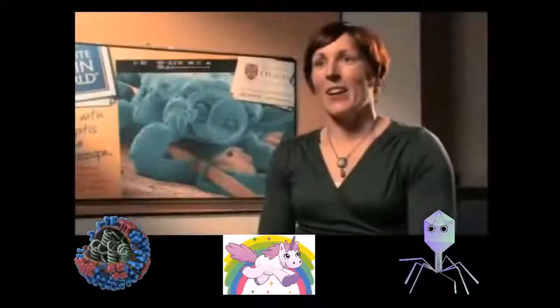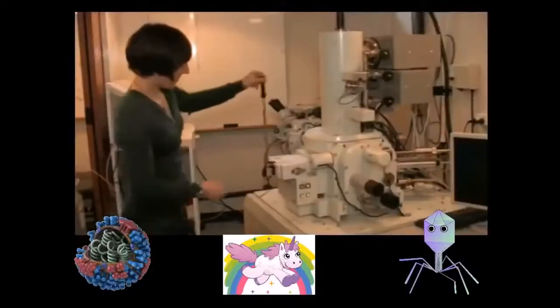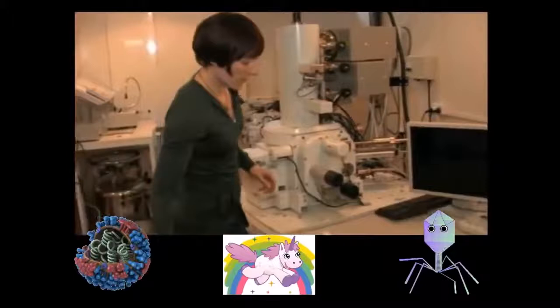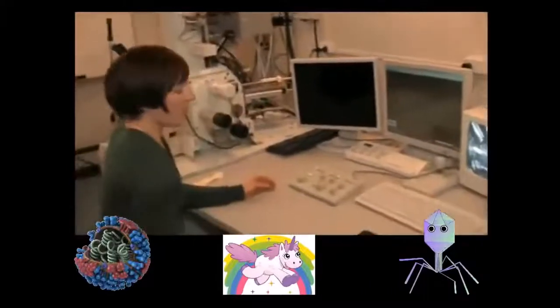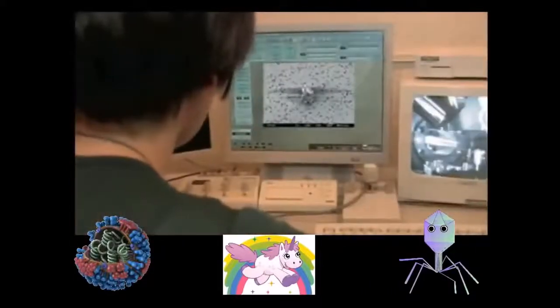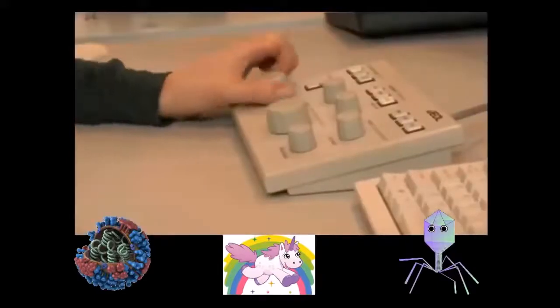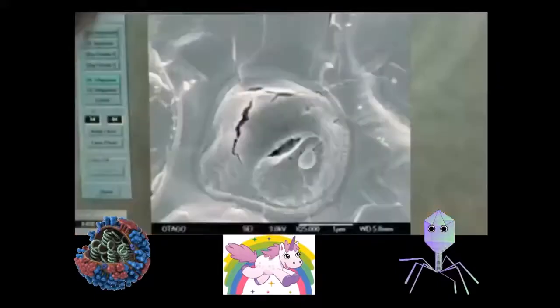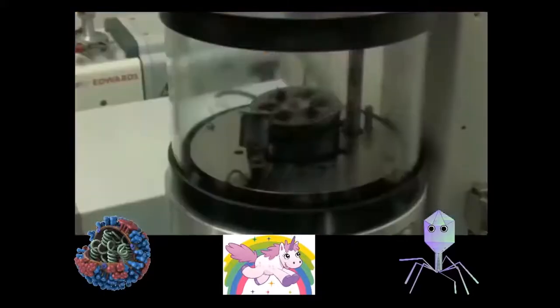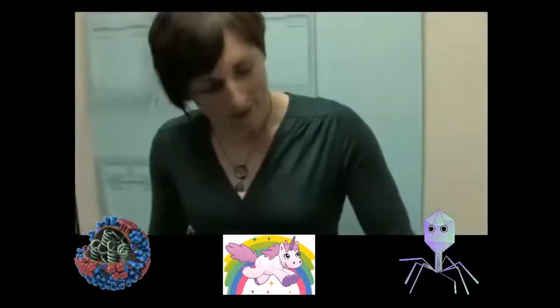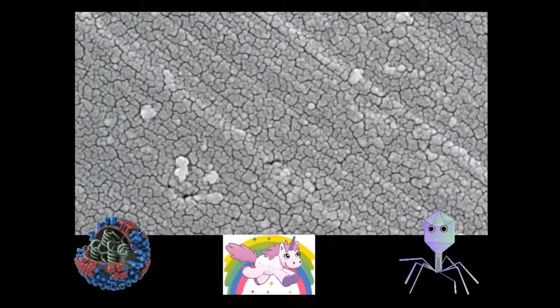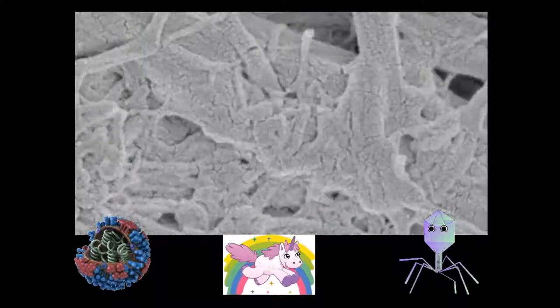It's quite important to be very open-minded about what you're going to say. You need to make sure what you're looking at is actually real, so you can get quite a few artifacts, anything from dust that's fallen on your sample, which can look like a piece of sample. You can get some cracking in the vacuum, so you actually get cracks forming in your sample, which are not there, they've been caused by the microscope. Sometimes the coating can cause artifacts. If you coat too thickly, you can start to see the metal particles. And of course, if you're looking for small particles, they can look just like your sample might look like.